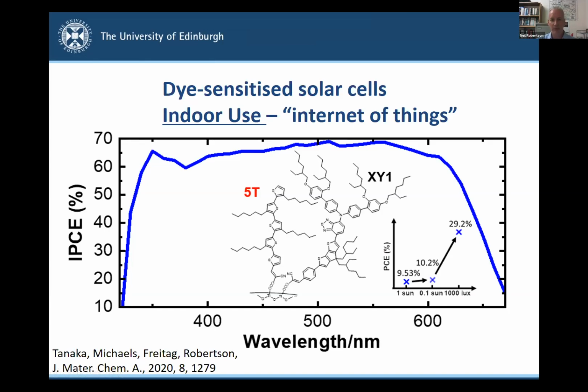So indoor light coming from LEDs or fluorescent lights is only really delivering light in this range. So the solar cells can be very efficient in this range, in fact, much more efficient than crystalline silicon. Here's a graph showing this: a dye-sensitized solar cell under one sun gives about 9.5% efficiency. However, in 1000 lux, which is an indoor lamp, nearly 30% efficiency.